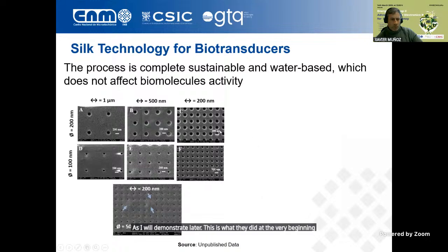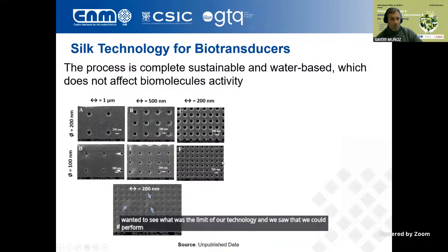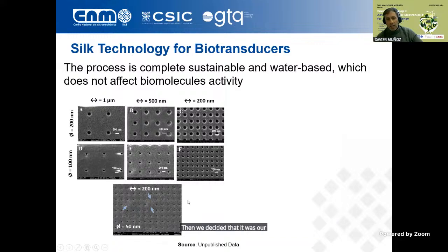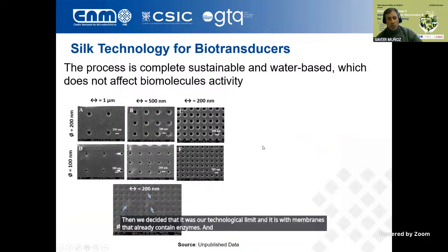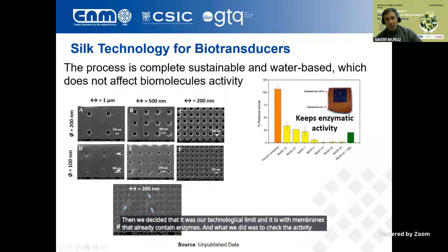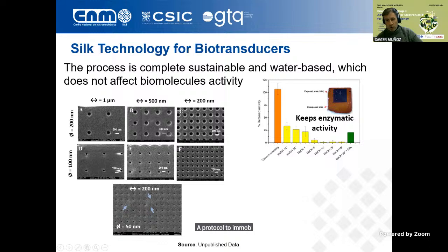This is what we did at the very beginning. We wanted to see what was the limit of our technology, and we saw that we could perform patterns of around 100 nanometers. Below that, it was difficult because sometimes the pattern was not perfect. Then we decided that it was our technological limit, and it is with membranes that already contain enzymes. And what we did was to check the activity of these enzymes after the processing. And what we saw was that the processing itself, the EBL processing, was not affecting the activity of the enzyme. Then we had a protocol to immobilize biomolecules without affecting them.